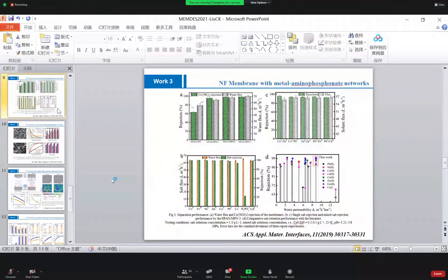So we tested the nanofiltration performance with these membranes, and we used both the APN and MPN modified membranes, using cobalt solutions as the feed solution, and found that the APN membranes show both lower rejections of the metal ions and lower water flux as compared with the MPN membranes.